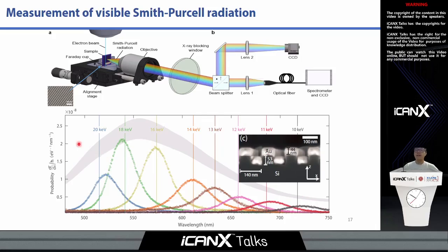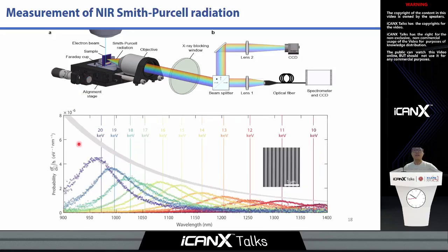We do a complementary measurement in the near infrared. I use a different structure with a longer period. This time, we see that the emission probability has a nearly monotonic reduction towards the long wavelength. This time, the material response is much flatter in this spectral window compared to that in the optical regime, but the reduction of the brightness of the electron gun still persists, which accounts for this reduction of the emission probability. Aside from these experimental verifications, there are also a few predictions pending experimental confirmation from our upper limit.